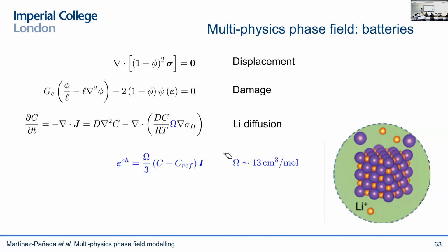One is that the toughness doesn't seem to depend a lot on the lithium concentration, unlike the case of hydrogen. The other one is that this partial molar volume is much higher, an order of magnitude larger, which means that those chemical strains that are present in hydrogen but negligible become very relevant here. In fact, there's no mechanical load being applied here. It's just the lithiation and delithiation which causes these chemical strains and therefore the appearance of cracks.